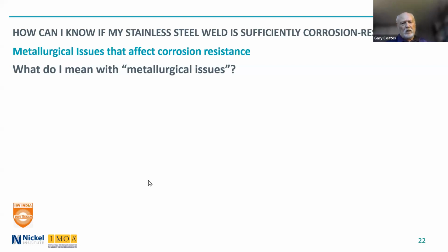And whether passivation is also required after pickling, that is a very interesting question, because there are people that will insist that once you pickle it, you need to passivate it. And the truth is that if you pickle it and the surface is clean, there's no oil and grease on it, so that the pickling action works, it removes all the contamination on the surface. It will passivate well in air. Now, if you do a chemical passivation through, let's say, nitric acid, it does increase the thickness of the oxide layer. It does make it more corrosion resistant, but I have to say only marginally more corrosion resistant. And so it's not really needed in most cases.